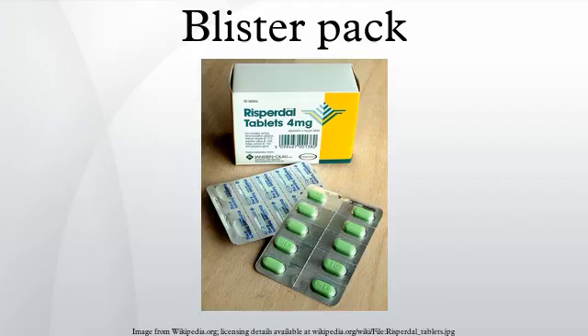Medical blister trays differ from pharmaceutical blister packs in that these are not pushed-through packs. The thermoformed base web is made of a thicker plastic sheet, generally between 500 microns to 1,000 microns, and cannot be collapsed, thus forming a solid tray. The lidding film provides a peel-open feature and is generally porous to allow sterilization. Such medical blister packs are used for medical devices used in hospitals.